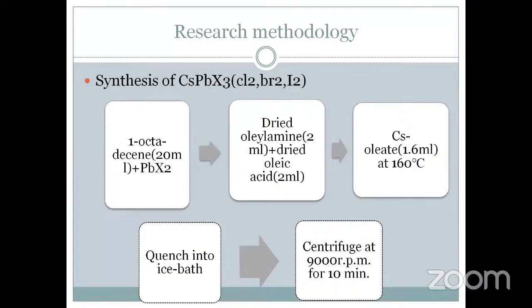In this method, 20 ml of 1-octadecene and a very small amount of PbX2 were loaded into a 100 ml 3-neck flask and dried under N2 gas purging for 1 hour at 120 degrees Celsius. After that, 2 ml of dried oleylamine and 2 ml of dried oleic acid were injected into the mixture. Now, after the complete solubilization of PbX2, 1.6 ml cesium oleate was injected at 160 degrees Celsius. Quickly after 10 seconds, the mixture was quenched in an ice water bath, and the temperature was decreased to 30 to 40 degrees Celsius. Now the mixture was centrifuged at 9,000 RPM for 10 minutes.